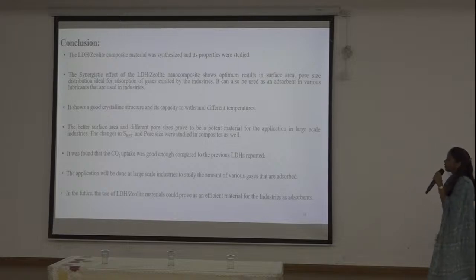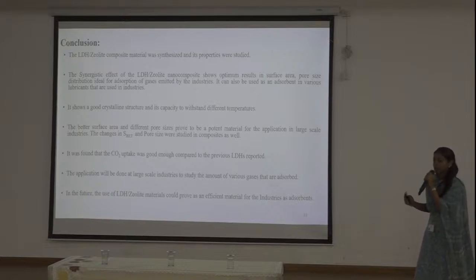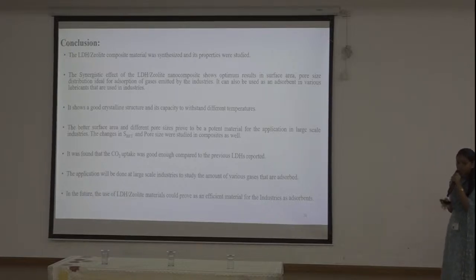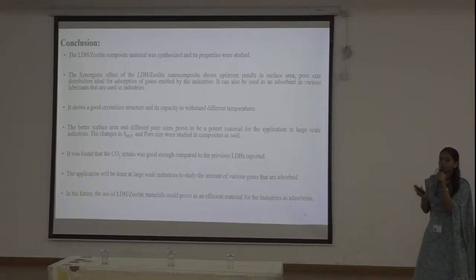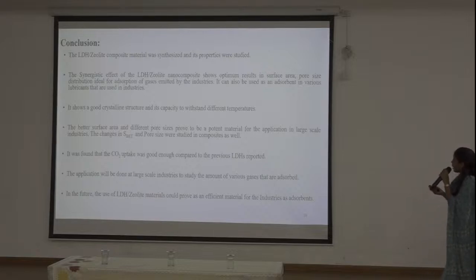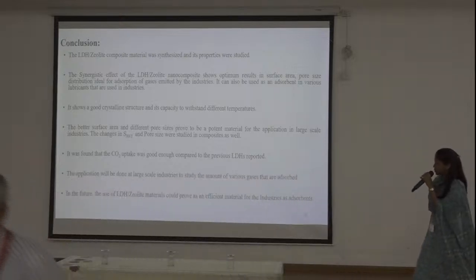So the prepared composite was prepared and all characterizations were studied. I would like to conclude that the synergistic effect of both the LDH material and the zeolite material shows optimum results in terms of surface area, pore size, and adsorption compared to other materials, and also showed a good crystalline structure and capacity to withstand temperature.